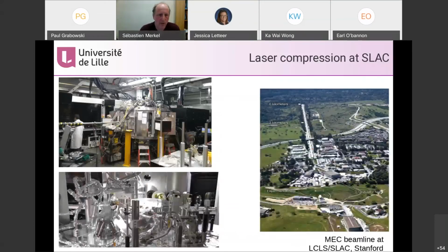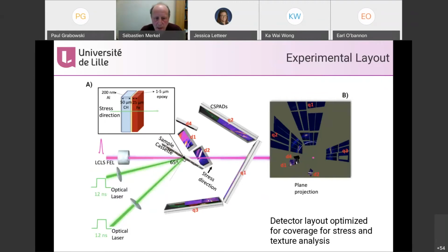And so we did the experiment at SLAC on the MEC beamline. We had the sample holders with many targets, so we could repeat the experiment. What was different in this experiment was the layout of the detectors. The detectors were laid out in a way that we could get maximum coverage of orientation for texture and stress analysis. So Cindy Bolmer and Ariana had thought very hard on how to place all of those small detectors and large detectors around the sample, so we could get an idea of stress and texture.